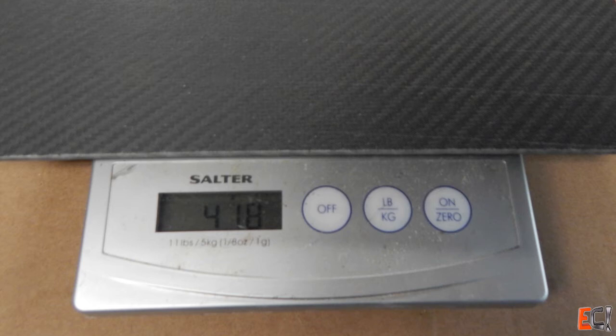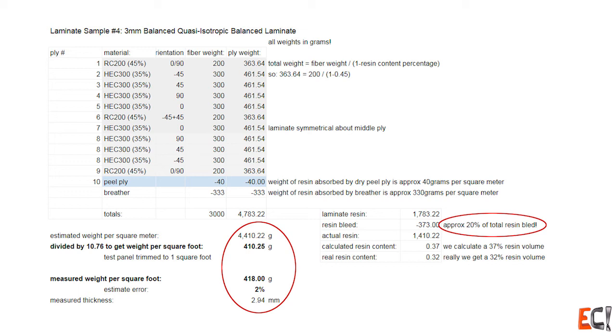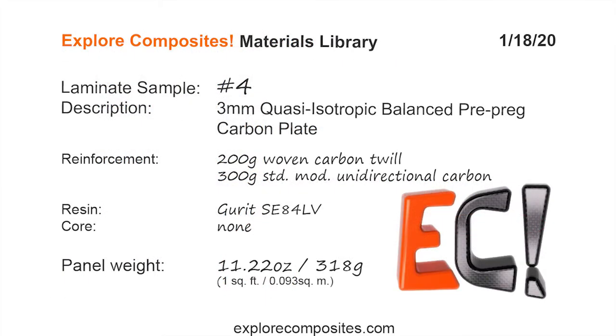Panel came out nice. If I had ramped it quicker and got it to kick before the resin ran so much it would have been better but you can see here the total outcome. The weight is about 2% error in the estimate. The thickness just under 3 millimeters probably explained by the excess bleed. And I did bleed almost 20% of the total resin out into the bleed stack which is kind of crazy. So there it is. Thanks for checking it out.